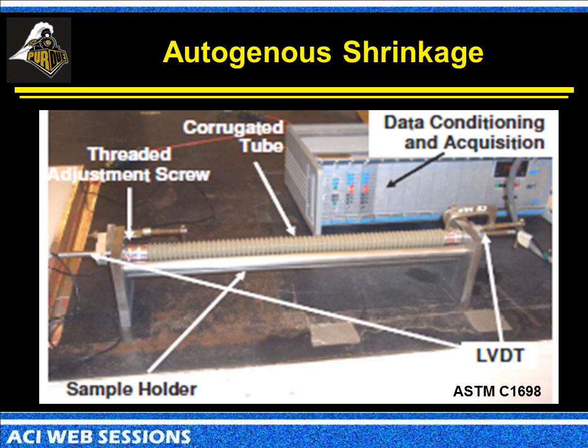So this here is the corrugated tube protocol, which recently became an ASTM standard. The idea here is you place the fresh mortar inside of the system, cap both ends of the system, and you can actually measure this while the system is fluid. We normalize all the results to look at these when time of set starts to occur, because as soon as it starts to set, then we're going to start to build up stresses inside of the overall system.